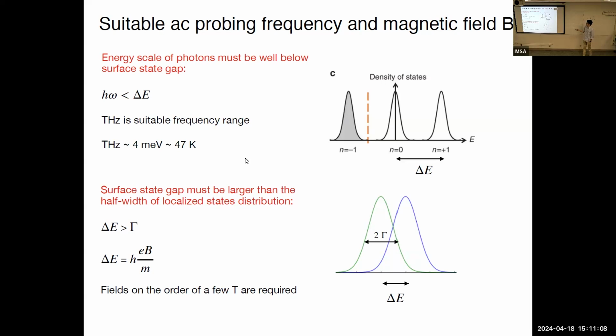Another thing is sometimes this distribution of a single Landau level is super disordered because of all sorts of impurities, and you also want to make sure that this spacing between the two adjacent Landau levels is actually larger than their widths, because if it's smaller, then you cannot tell them apart. Which sets some limitations on the magnetic field which should be applied to see this effect, because this delta E is actually directly proportional to B. It's equal to h bar eB over m. So that is the second thing to think about.